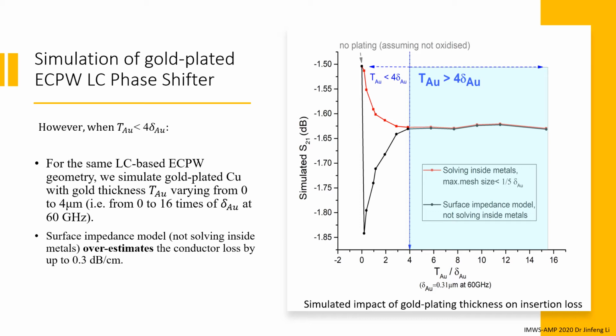For the same liquid crystal-based ECPW geometry, we simulated gold-plated copper with gold thickness changing from 0 to 4 microns, which is from 0 to 16 times the gold skin depth at 60 GHz. The simulation results in the figure present S21 versus the ratio of the gold plating thickness to gold skin depth at 60 GHz. It is clearly observed that the traditional surface impedance model fails to accurately model the gold plating cases when the gold thickness is thinner than 4 times the gold skin depth. Instead, it overestimates conductor loss by up to 0.3 dB per cm.